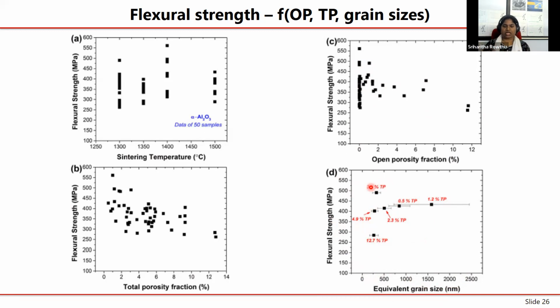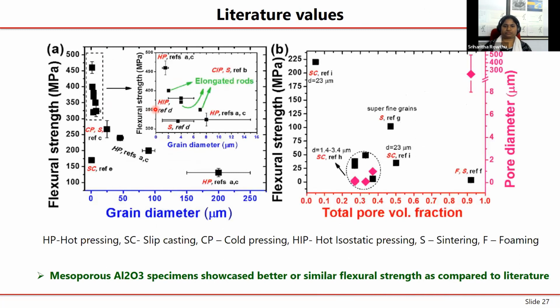However, what we can take as a key message is that the flexure strength values of these porous materials are as high as 550, but they can be as small as around 250 megapascal. With that key message, let us see what the literature values of alumina samples look like. If we look at that, then actually you see that these are all the literature data that I have picked up from several sources, and I have plotted them. So firstly, the flexure strength as a function of grain diameter is plotted, and you actually see that this is a very nice sort of a trend that follows.